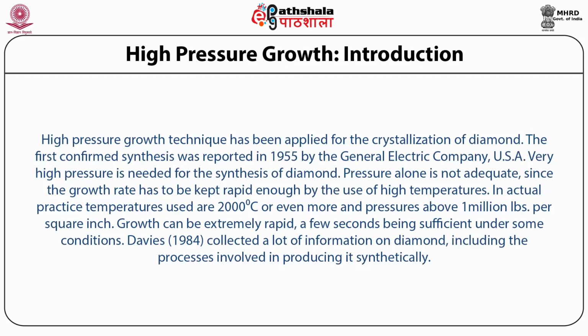Pressure alone is not adequate, since the growth rate has to be kept rapid enough by the use of high temperatures. In actual practice, temperatures used are 2000 degrees centigrade or even more, and pressures above 1 million pounds per square inch. Growth can be extremely rapid, a few seconds being sufficient under some conditions. Davies in 1984 collected a lot of information on diamond, including the processes involved in producing it synthetically.